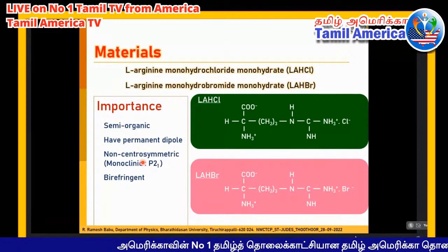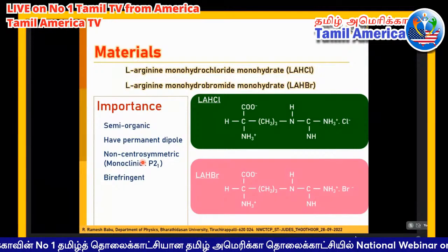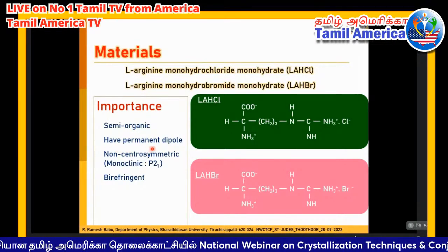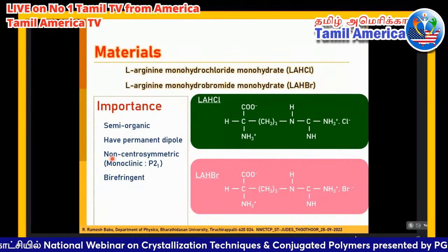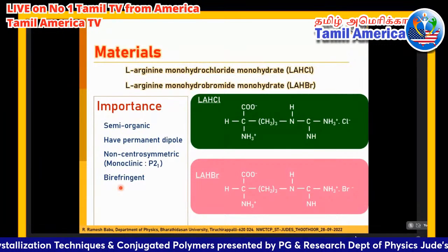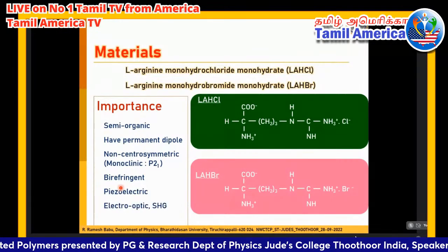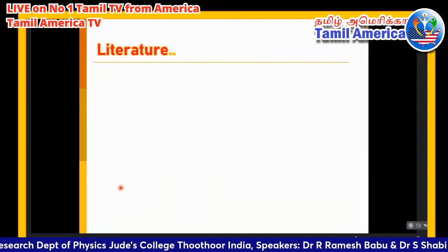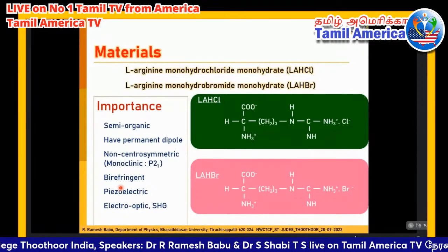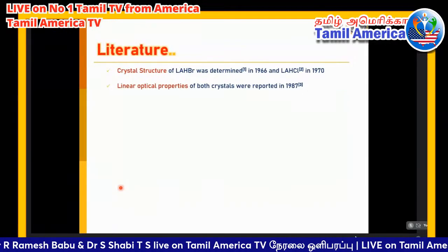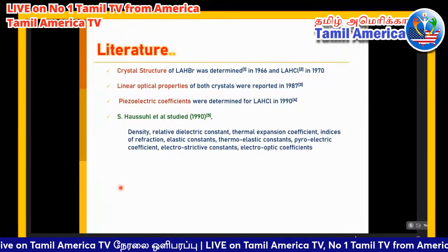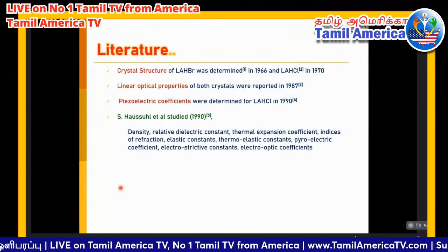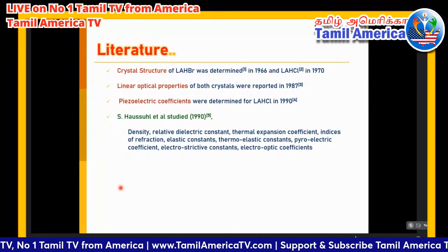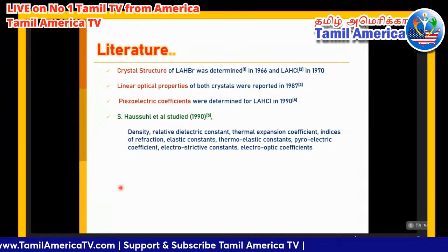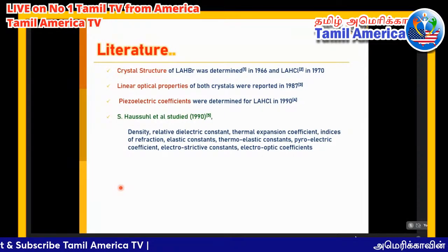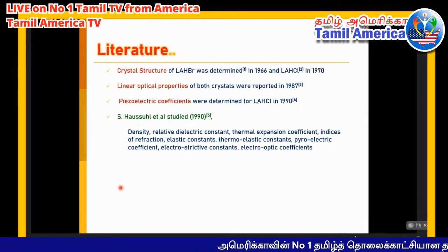These materials have very many advantages. They come under the category of semi-organic, show a permanent dipole moment, and crystallize in a non-centrosymmetric crystal structure. They also exhibit birefringent, piezoelectric, electro-optic, and second harmonic generation properties. So we made a literature survey on LAHCl and L-arginine hydrobromide, these two materials. We found there are very many literatures available. These materials were crystallized in 1966 and 70 respectively. Haussuhl et al. studied very many properties of LAHCl. Even though they studied different properties of these materials, the grown single crystals were only a few millimeters in size.